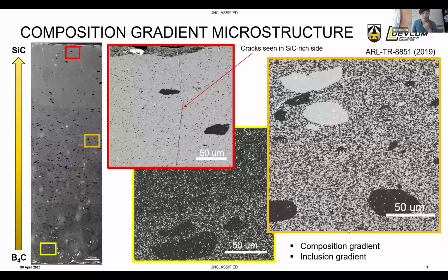So this is that same functionally graded part that I showed in that second column in the previous slide. But this is after we sintered it, we sliced it in half, and then you could see that cross section through SEM imaging. So the darker material will be the boron carbide, the brighter material will be silicon carbide. So you can begin to see how that composition changes. Our mixing isn't bad, but not great, right? If you remember from the printer, we had a simple auger design, and it's generally about a 2-inch mixing area. That auger is only about 2 inches in length.